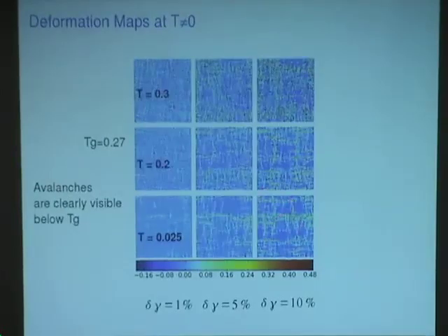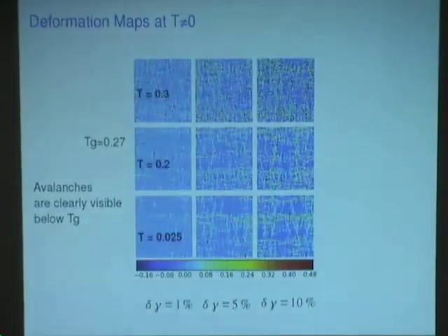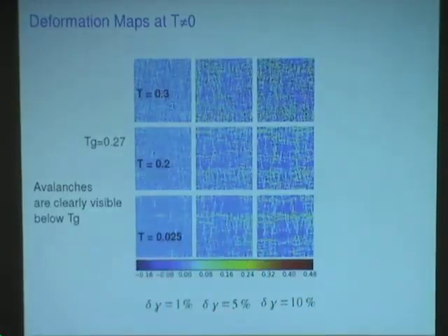The point, Jim, is that we use these Lees-Edwards boundary conditions. And what these boundary conditions do is force the system to be invariant by translation. And of course, that's very different from any experimental situation. In fact, we are working really hard to avoid any form of localization which would last. What we see, which is interesting, is that the system spontaneously is trying to localize, but we force it not to.